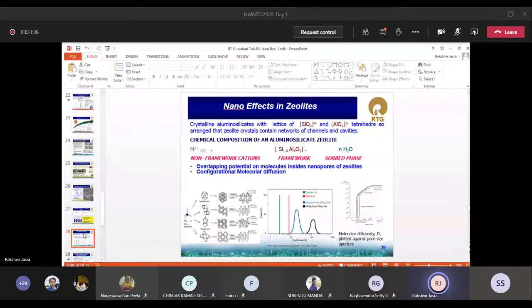As I said, zeolites are aluminosilicates which have got uniform sized pores and they're all interconnected pores. And most of the pores, or almost all zeolite pores, are less than 10 angstrom. So it means most of the molecules are also less than 10 angstrom. So they can be really selective at a molecular size or shape level. So that's why they are also called molecular sieves. And diffusion here is also configurational diffusion because of this small size. The pores are of similar size to the molecule, so diffusion is a little different here. So we can really create selectivity or a selective catalyst using zeolite because of their size and shape, which is close to the molecule, and then also because of diffusion.